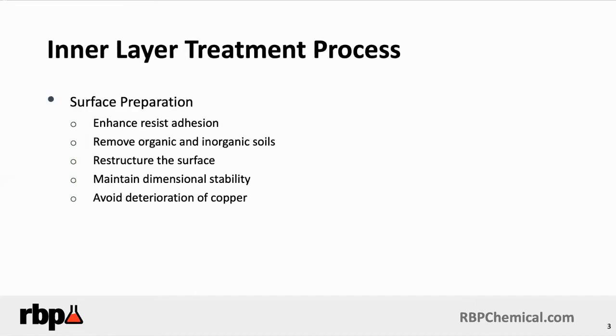So surface preparation, and you'll hear this from me really throughout the troubleshooting process. A clean virgin copper surface is paramount in order to get good quality, whether it's plating, a circuitized inner layer or outer layer, or even just to get fine line images, like 3 mil lines and spaces and below. You've got to have all the other aspects of imaging aligned, of course, but surface preparation is the one I really want to concentrate on here, because this is where I see a significant source of yield loss, not just in photoresist adhesion and the photoresist process, but also in the plating process, as you've heard in some of my other podcasts. So surface preparation is going to be the key. This is what's going to prepare the copper surface so the photoresist can easily adhere to it prior to going into the exposure process.